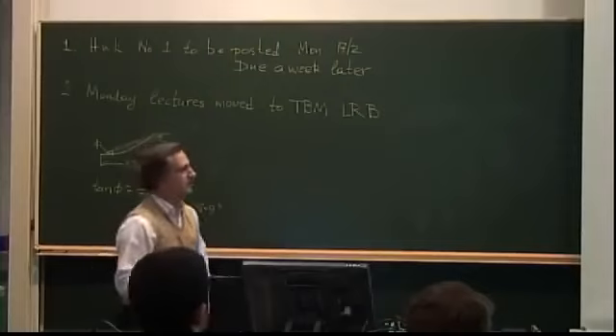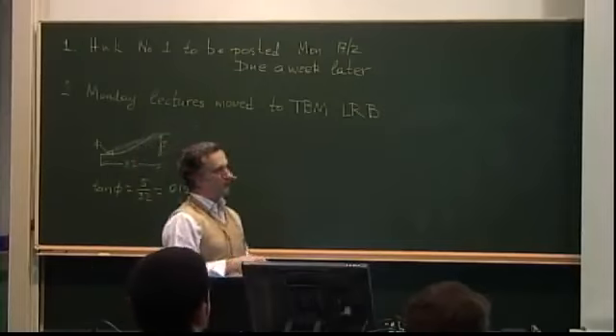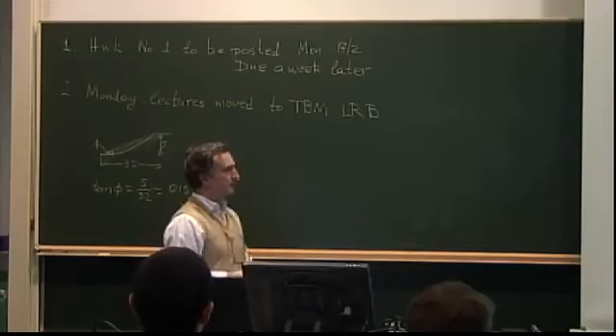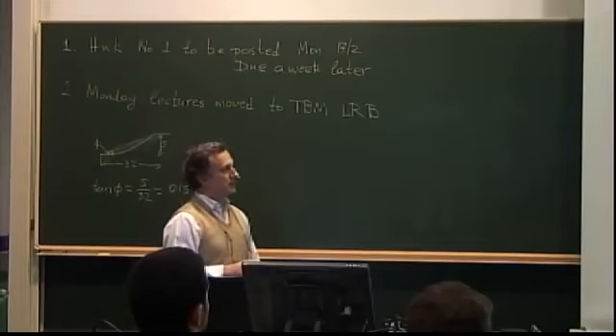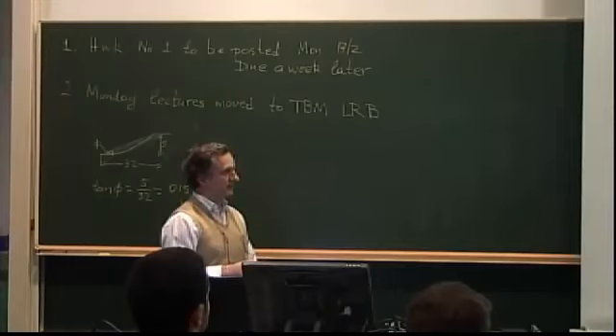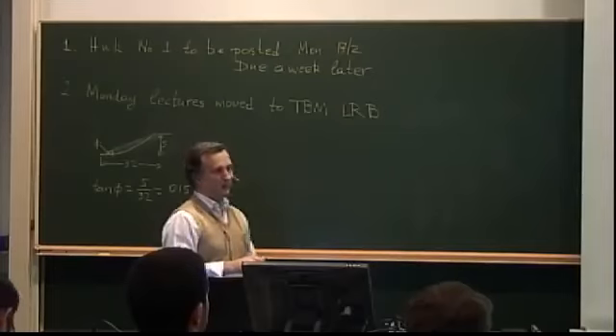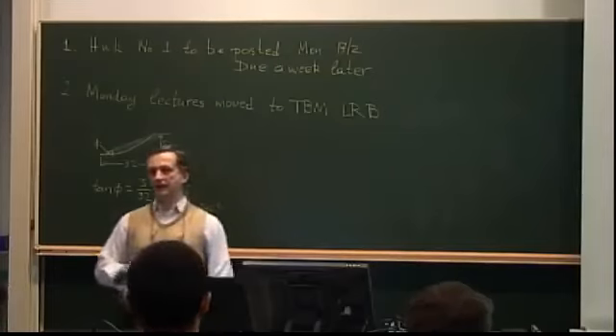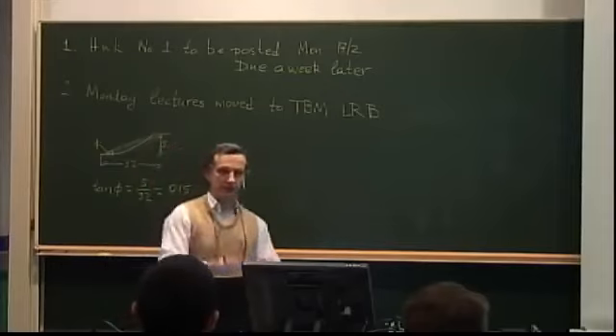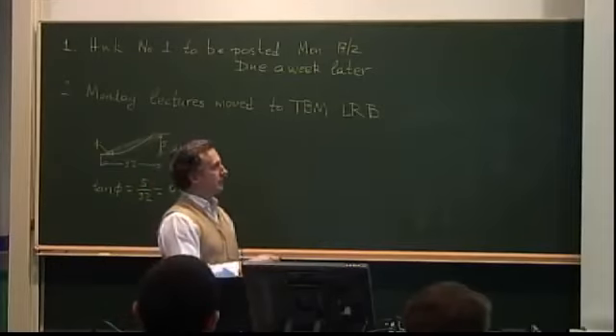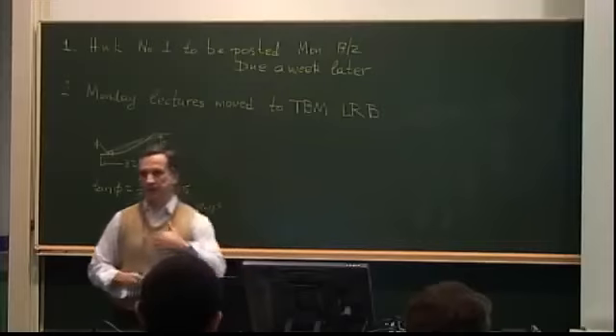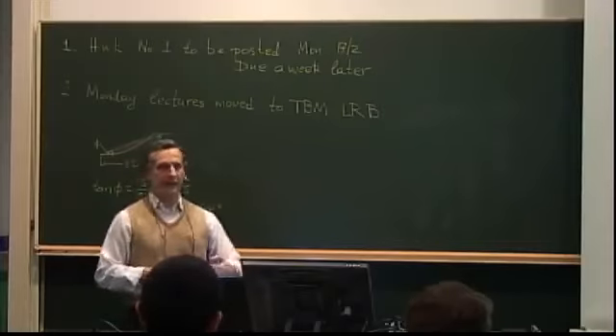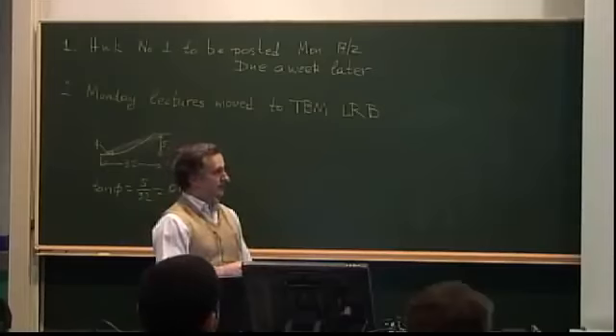But that in and of itself doesn't mean much, because you can show analytically, and tests support this, that all that means is you have a zero stress at the bottom here of this top part of the fiber, or at the top of the other half, and that within a very short distance away from that cut or crack, the matrix will transfer by shear all the load back to that fiber. So a single cracked fiber means nothing really, other than locally you had a stress concentration which increases the load in the adjacent fibers.